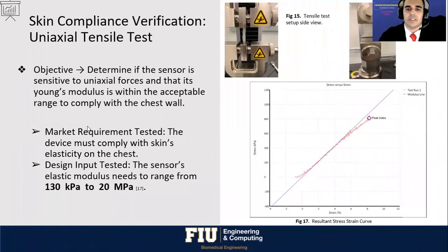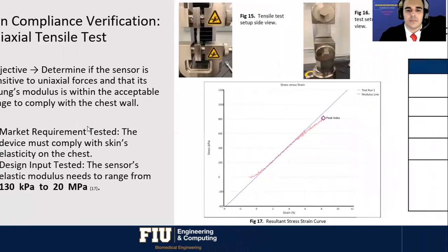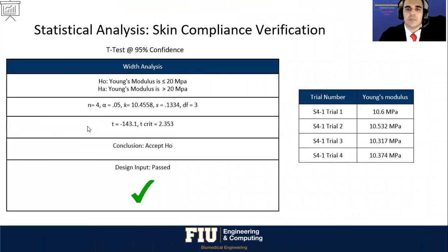The next verification test conducted was a tensile test. The goal was to test if the device has a low enough elastic modulus, such that when a person's chest wall would move due to the heart, the device would stretch alongside the skin, reducing tension forces. Using the same t-test as before with 95% confidence, we tested a 22 by 31 size sample 4 times and had an average of 10.5 megapascals, which is sufficient for compliance with the skin.